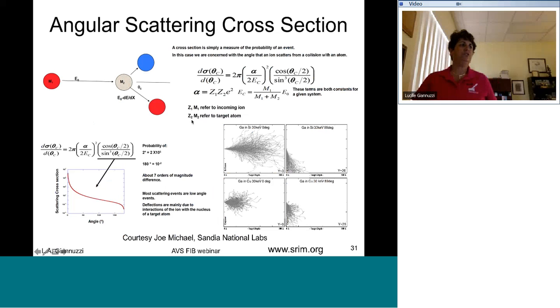So again, first, if we just talk about angular scattering cross-section, given by this equation here, we see again incoming ion M1 can hit your target. This makes the target move off one direction, and the ion can be pushed into another direction. Associated with this is an energy loss. This cross-section here is basically just a measure of the probability of an event. Okay, so if we're just concerned with the angle that an ion scatters, we see the scattering cross-section as a function of angle. We see that the probability of